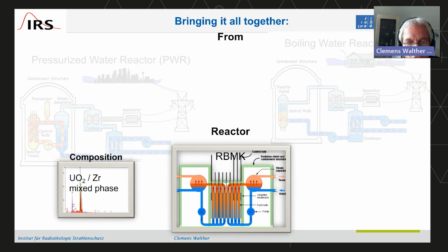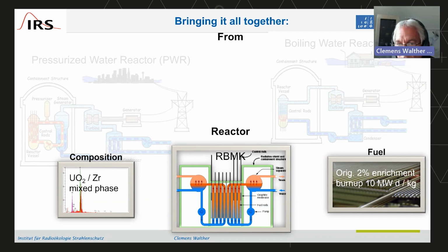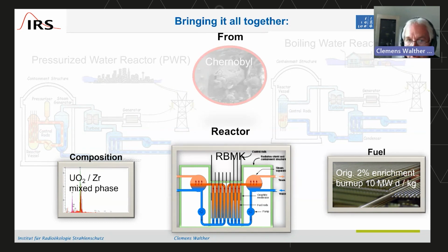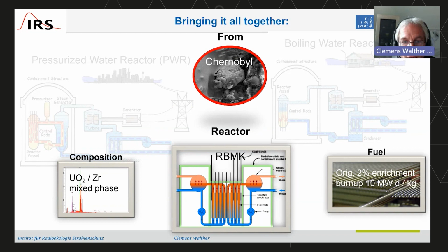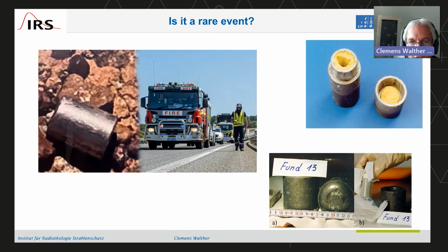We can tell the composition. I didn't show everything in detail, but we can tell from the EDX and other methods that it contains the uranium dioxide zirconium mixed phase in that particle. And we can also tell what kind of fuel was used, uranium oxide fuel with an original 2% enrichment, and we could tell how long it was used in the reactor, so a burn-up of 10 megawatt day per kilogram. And just remember that all this information was obtained from a few picogram of material, so really tiny, tiny amounts of material, and consumed less than a femtogram, so that particle is available for many other investigations, even after you did that nuclear forensics on it.